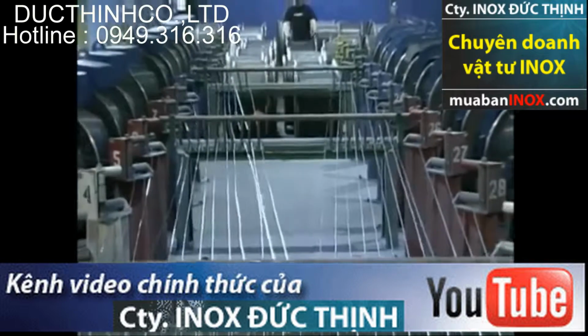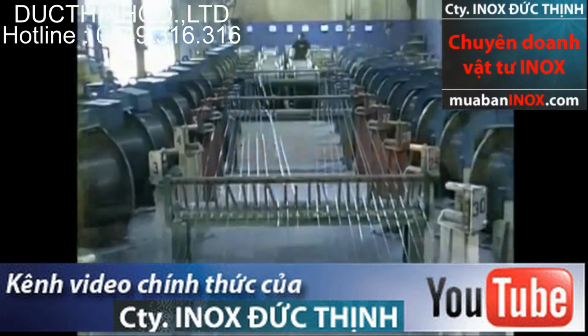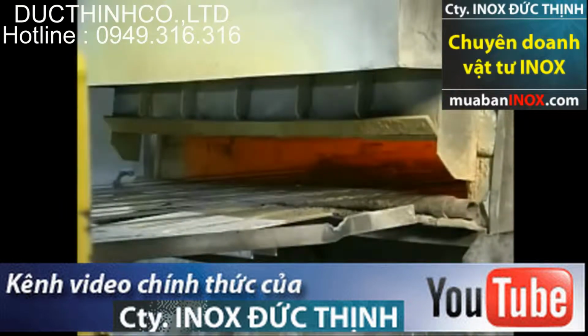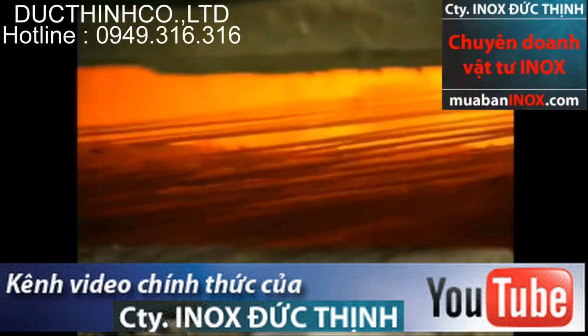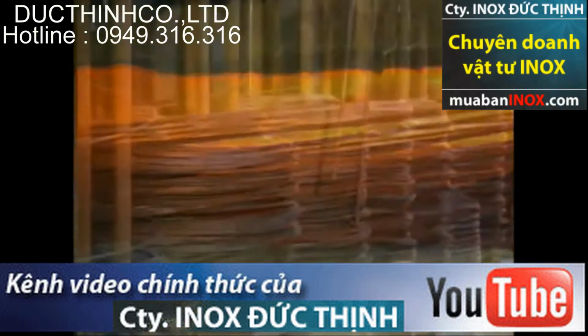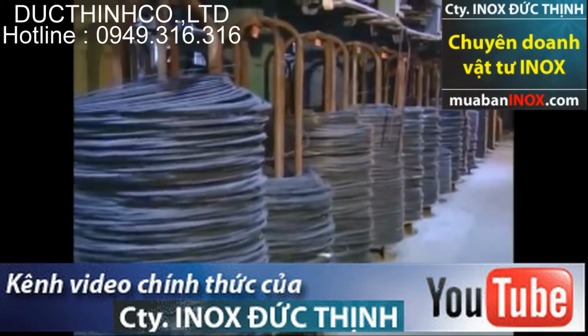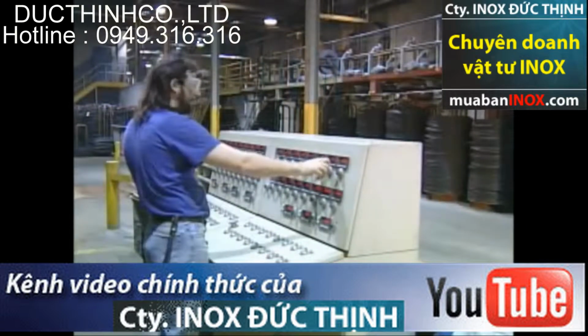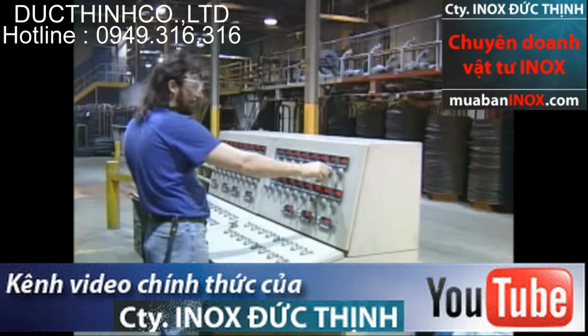Since any drawing process is limited to a specific reduction of area, the intermediate process wire requires heat treatment or patenting to provide the proper steel microstructure so the wire can be drawn to the final diameter. The patented wire is spooled onto formers and the precise specification carefully controlled to meet the tight tolerances of the final product. The patented wire is then tested, and a label is placed on the wire to maintain proper identification.